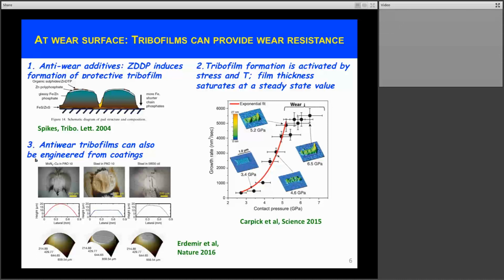And so on the next few slides, I want to illustrate these dynamical properties by looking first at what can happen at the wear surface, and then we'll look below the wear surface. So at the wear surface, for instance, we're talking about the formation of tribofilm. It is well known that additives such as ZDDP can promote wear resistance.